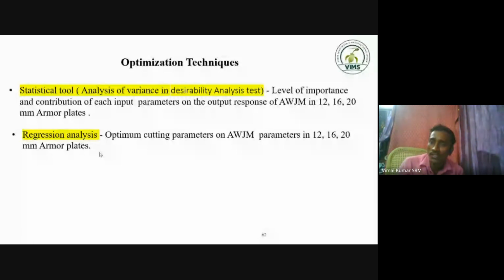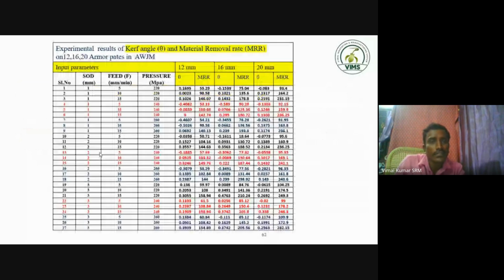If we work out with a particular thickness, we can utilize those values and use the new thickness of the material for the armor grade steel. In this condition, we can reduce the time and get the output values, for example in the machining condition: kerf angle, material removal rate, surface roughness. I will show that in the next slide. So here we already have the input values, SOD, feed rate, pressure for the three thicknesses of materials. These are the output values, theta, kerf angle, MRR for the 12 mm, 16 mm, 20 mm plates.